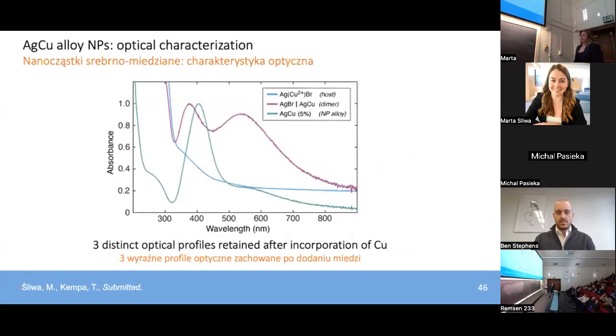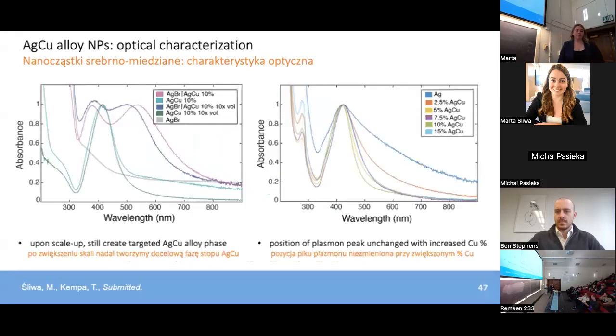We also characterize the products optically, as we have in an analogous way to the previous part of the discussion, and saw again 3 distinct profiles for the silver copper bromide with no plasmon peak, the 2-peak profile for the silver bromide silver copper nanoparticles, and again the recovery of that plasmon as we etch the silver bromide phase of the dimer. So even if we introduce copper, with this data here indicating what we see for 5% copper and silver alloy, we still have those very distinct plasmon profiles.